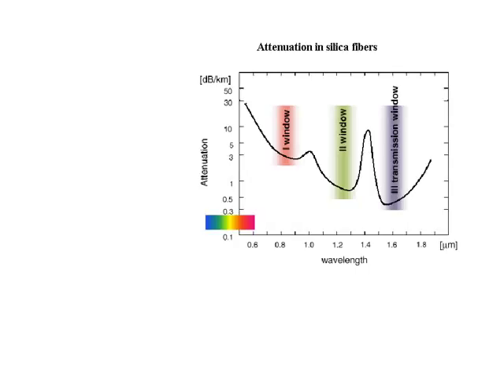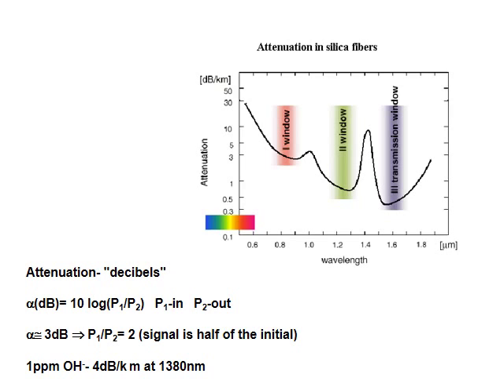You can also see in the figure the attenuation units used by telecom and fibers people. Decibel, or dB, is the unit used to report losses. It is related to our well-known chemical absorbance. The number of decibels is 10 times the logarithm to base 10 of the ratio of the two power quantities. You can also observe the peak occurring at around 1.39 micron for silica fibers. It is in fact related to OH groups occurring, and not desirable, in silica.